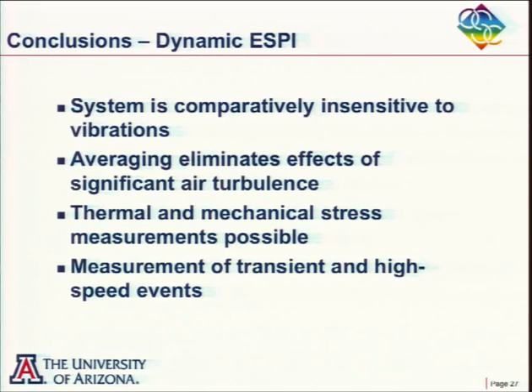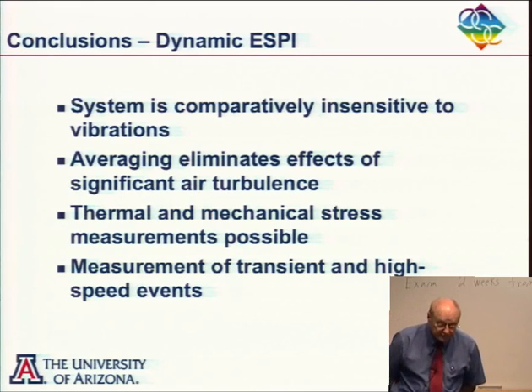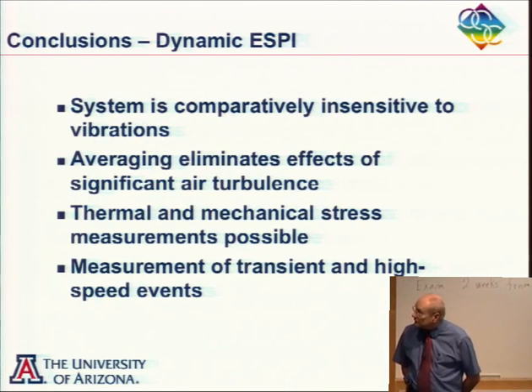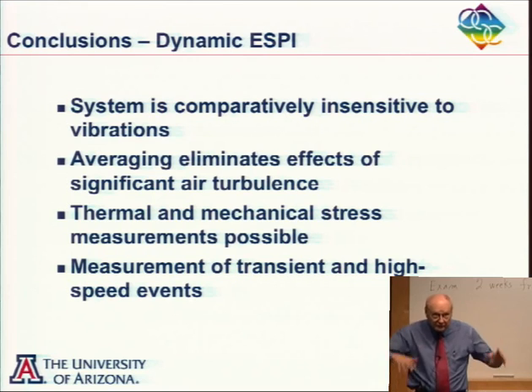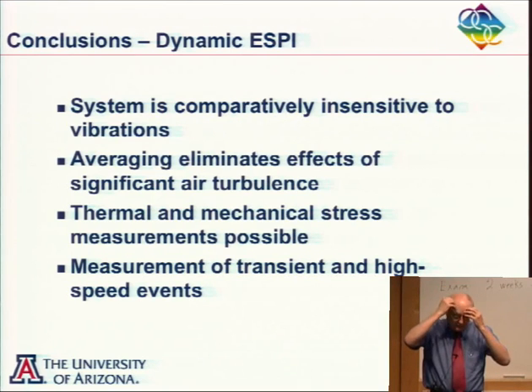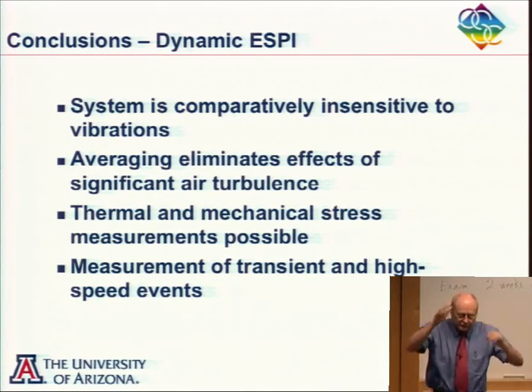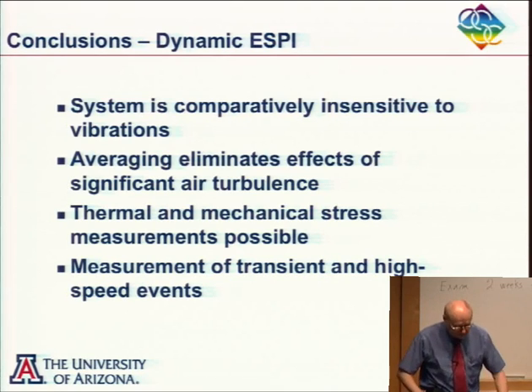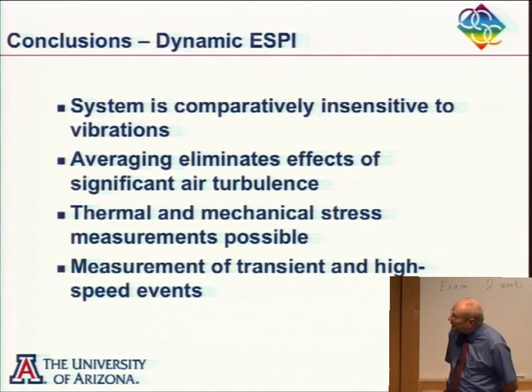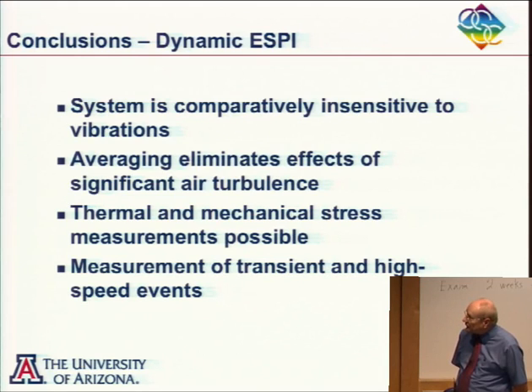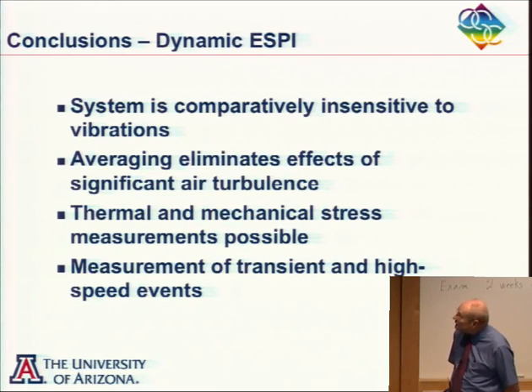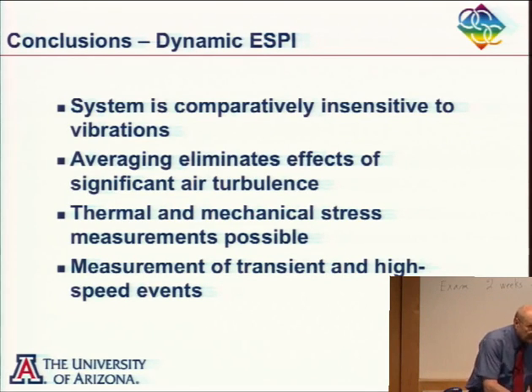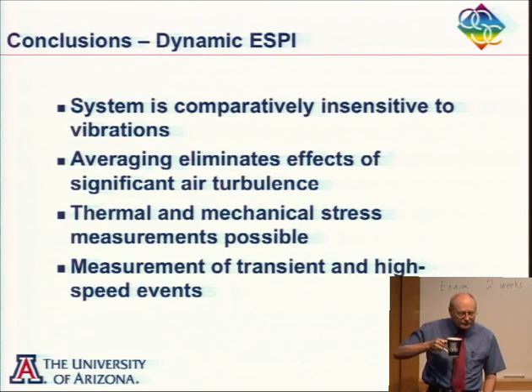This technique is pretty insensitive to vibration. Air turbulence, which drives you crazy, you get rid of by averaging — it's random. Sometimes you want to make the air turbulence worse by putting fans in the system to blow the air around so it's definitely random. And you can measure thermal-mechanical deformations quite well. That's the way you do holographic non-destructive testing nowadays.